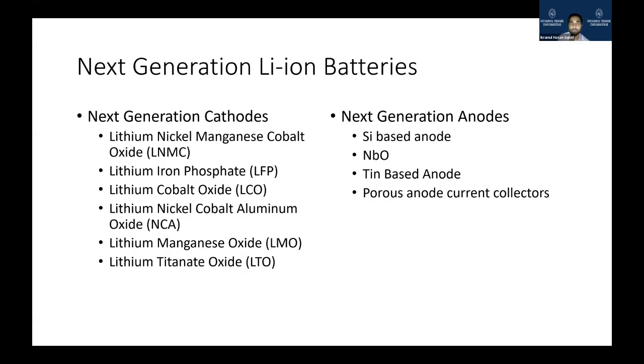So when you are repeatedly inserting and de-inserting lithium inside the system, this silicon degrades faster and delaminates faster, and that's why it separates from each other. That means the whole structure or continuity of the silicon breaks, and then the silicon battery degrades faster. So people are working on it now, and I am actually working on it as well. If we coat carbon on silicon, this cracking does not happen, or it is minimized to a level that we can cycle it for 1,000 times. Because nowadays, if we use a high silicon amount in the next generation anode, it can cycle 100 to 200 times, not more than this.